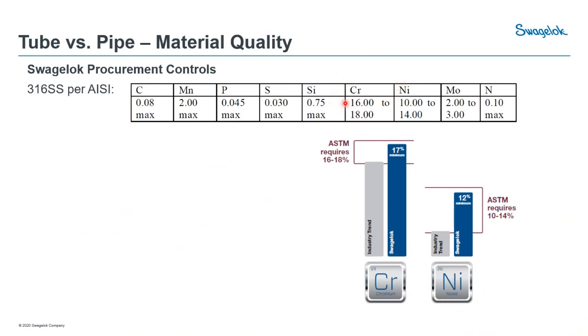So you might see 16.1% chromium and close to that 10.1% nickel. But really, we find that in certain corrosive environments, this has a drastic effect. And there's certain percentages that you really want to hit to ensure that performance. So for all Swagelok tube fittings, we'll have a minimum of 17% chromium and a minimum of 12% nickel. So this still remains compliant to the 316, but it elevates those so that you can ensure that performance.